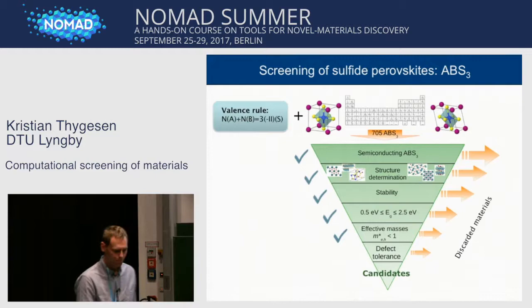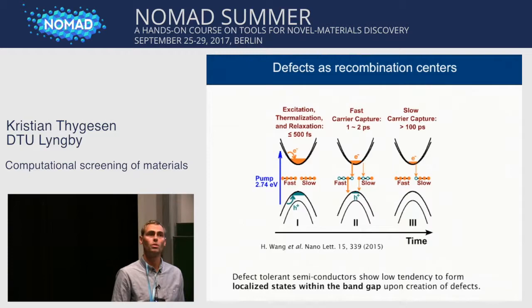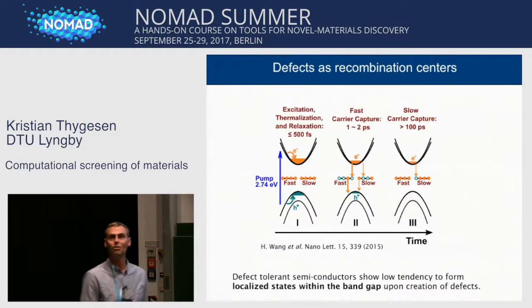So in reality, defects play a very important role, probably a much more important role than we would like to believe as theoreticians, because defects are difficult to treat in DFT calculations. They require large supercells, and therefore typically, at least in these high throughput screening studies, defects are typically not taken into account. However, they are really important.